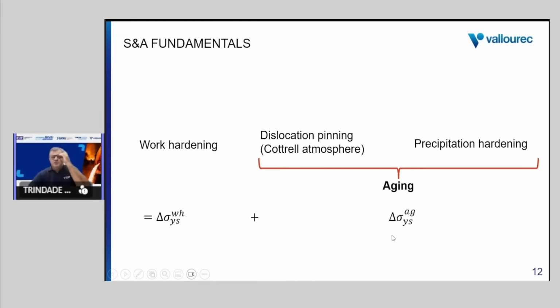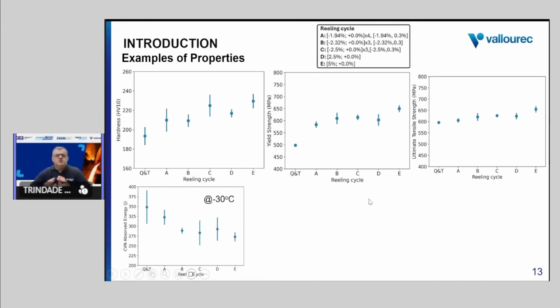When we are looking at the aging contribution, we can imagine two contributions. One is due to dislocation pinning, the formation of the Cottrell atmosphere, which we are going to discuss a little bit, and the other is precipitation hardening. So we will come back to this mechanism to see which one is more important.